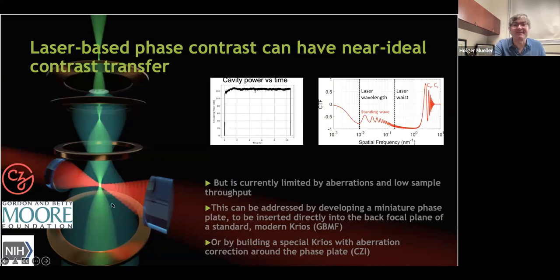The laser cavity is here, but notice the two graphs here. This one shows the measured cavity power versus time, and you can see it stays constant at 120,000 watts circulating in this cavity until we turn it off 10 hours later with no apparent drift or deterioration whatsoever. In fact, our phase plate has accumulated hundreds of hours of operation and shows no deterioration.